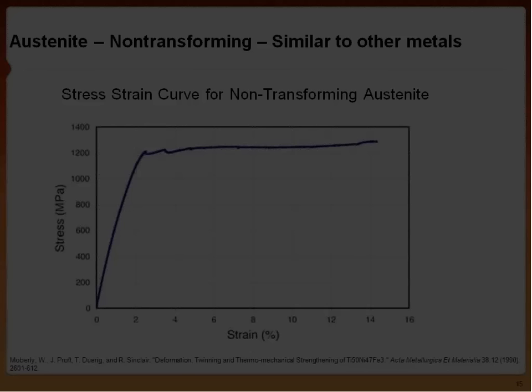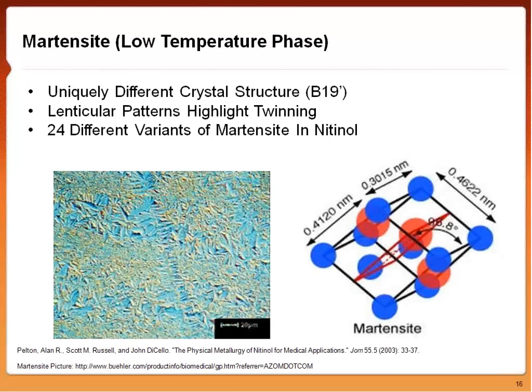The other phase I want to talk about for nitinol is the martensite phase, which is the low temperature phase. It's a uniquely different crystal structure than austenite. When you look at the optical TEM picture down here, you see it at a much larger scale, and it has these raised ridges, which are actually lenticular patterns highlighting twinning. Twinning is the main mechanism by which the shape memory and superelastic effects occur.